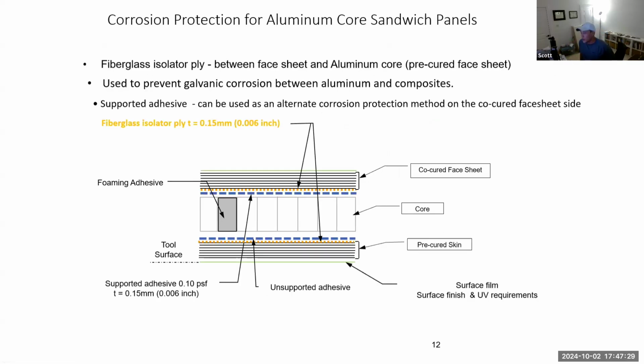So another thing that we need to take into account as engineers is galvanic corrosion. Carbon and aluminum don't get along, but our honeycomb composite bond panel consists of an aluminum core and the face sheets are carbon, right? So they're going to be interfacing together, and that leads to galvanic corrosion on the aluminum part. So in order to prevent that, which is the degradation of the material, as much as possible, they add a fiberglass isolator ply between the face sheet and aluminum core, used to prevent galvanic corrosion, as I mentioned. Supported adhesive can also be used as an alternate, particularly on the co-cured face sheet side, this face sheet that doesn't have the perforated holes.